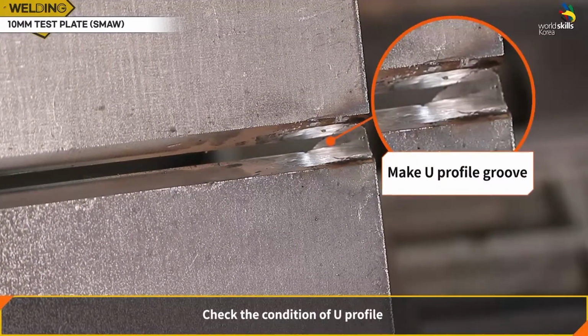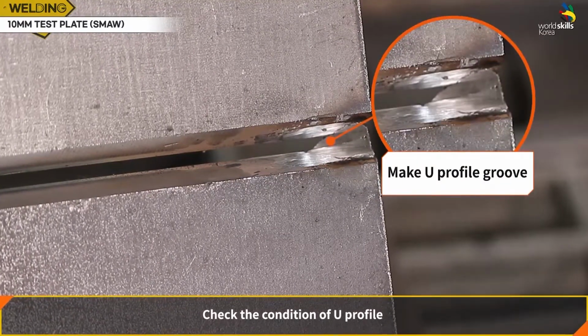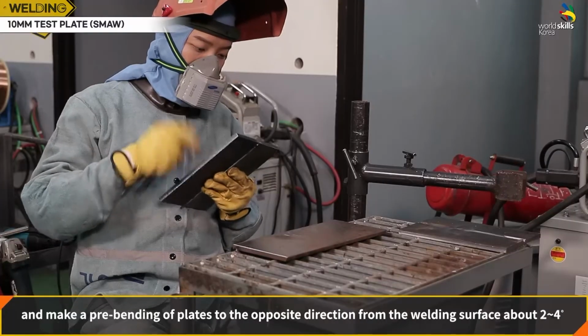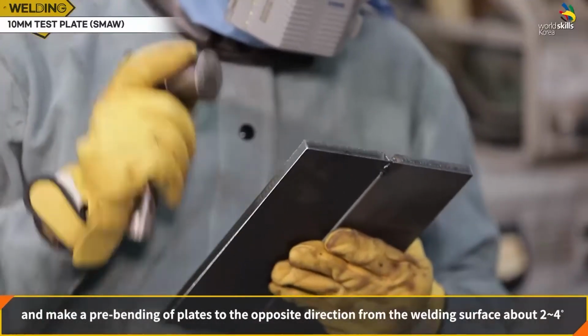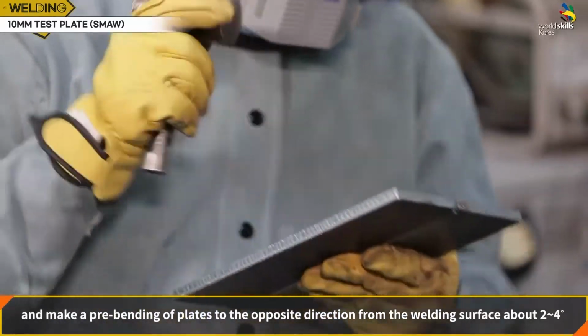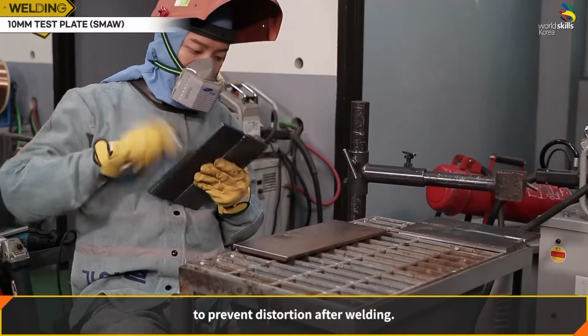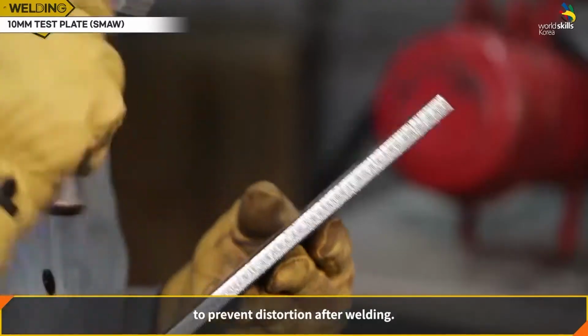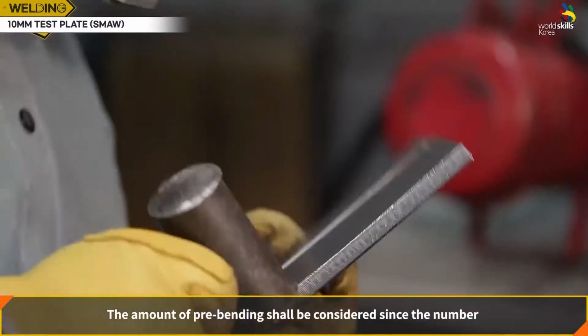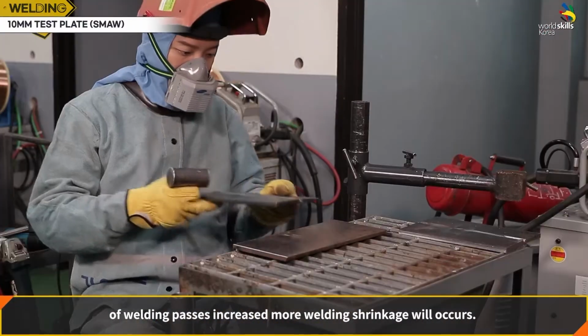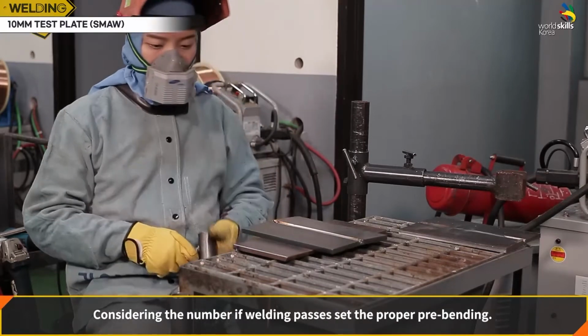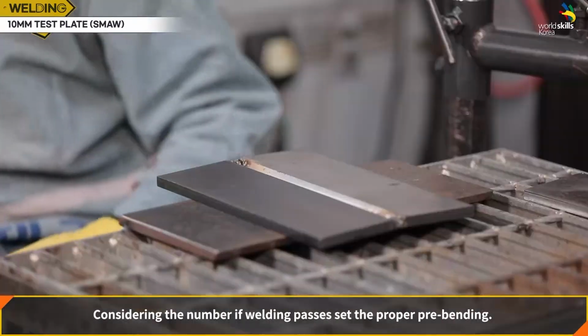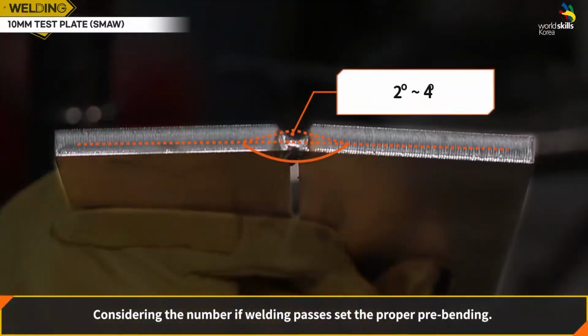Check the condition of the U-profile and make a pre-bending of plates in the opposite direction from the welding surface, about 2 to 4 degrees, to prevent distortion after welding. The amount of pre-bending shall be considered since, as the number of welding passes increases, more welding shrinkage will occur. Consider the number of welding passes and set the proper pre-bending.